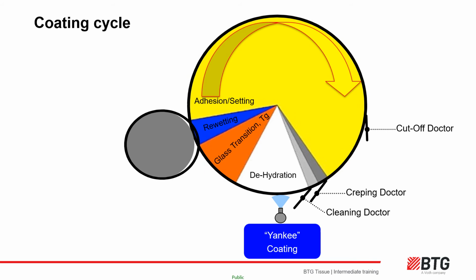Finally, if there is a cleaner blade in use, the cleaner levels off the coating debris left behind. Some residual coating and contamination will become baked into the hard coating layer each pass. The level coating layer is then in a better condition to accept a fresh application of coating from the spray bar, and so the process repeats.